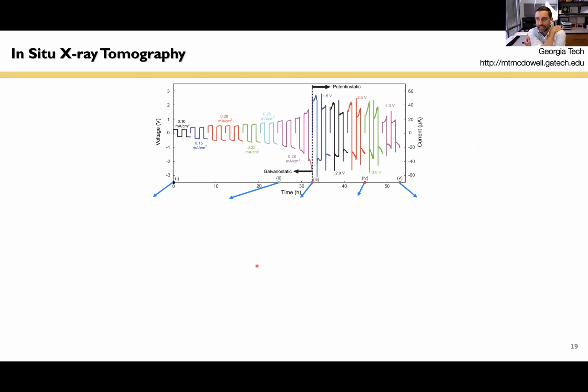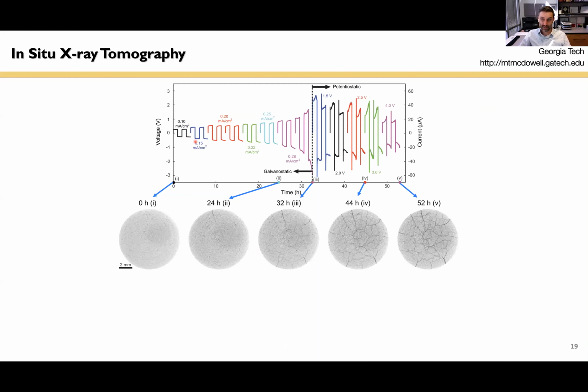To investigate the impacts of interphase formation, we carried out some more X-ray tomography experiments. These were slightly different. They were carried out in a lab scale tomography instrument rather than a synchrotron. The resolution is a lot worse, but the idea is the same. In this particular material, we took lithium metal, we sandwiched this LAGP pellet with lithium metal, we cycled it back and forth kind of like we did before, as I showed you. And these are now X-ray image slices from the middle of this LAGP pellet as we cycled this battery over 52 hours. So it's a longer experiment.